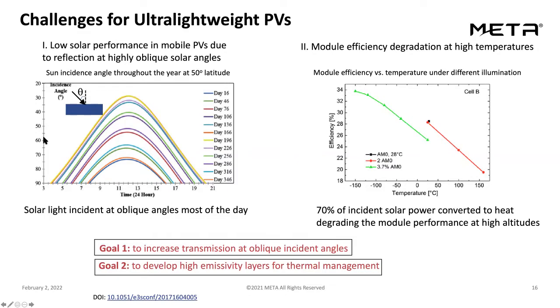And that becomes actually a major challenge in maintaining the efficiency of the solar cell throughout the day. Another challenge, especially for high altitude systems like UAVs, is the heating up of the modules. So this is showing the efficiency as a function of temperature, and you can see basically a significant degradation. So for next generation solar cells, these two problems have to be handled properly.